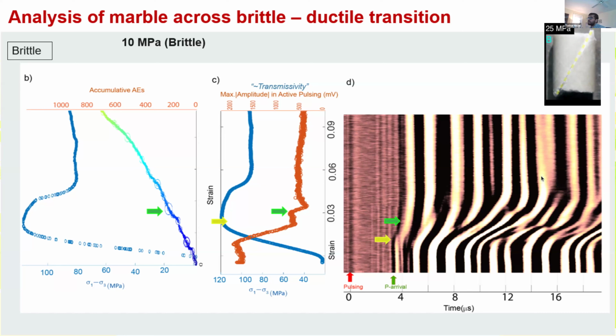And then there's even some changes in the coda that's occurring subsequently as the sample continues to yield more plastically. There's going to be some changes in the p-wave arrivals. If we just follow the time period that's showing the p-wave arrival on the figure on the left, you can see that right around the time period where we go from elastic to brittle deformation and then plastic yielding, there's a change in the p-wave, but that initial p-wave arrival doesn't continue to evolve too much. There's maybe subtle changes, but it's not changing a lot.